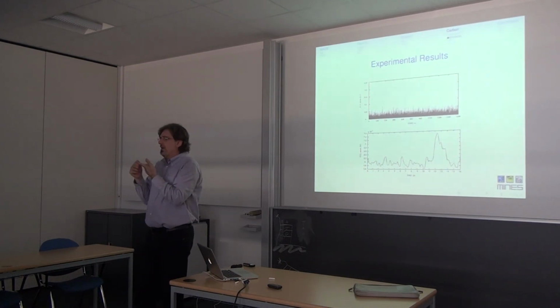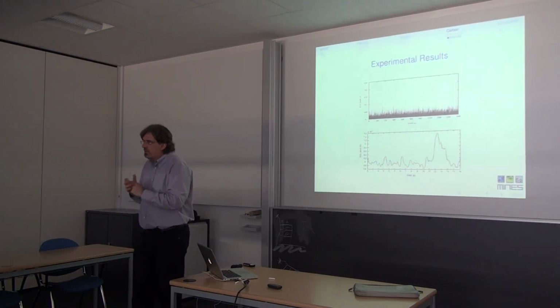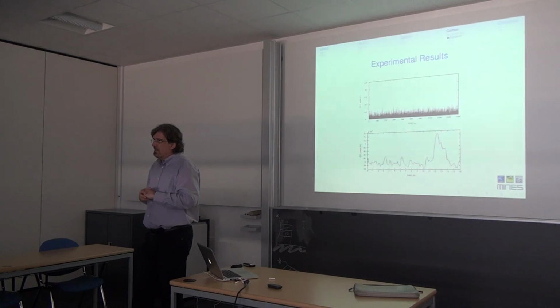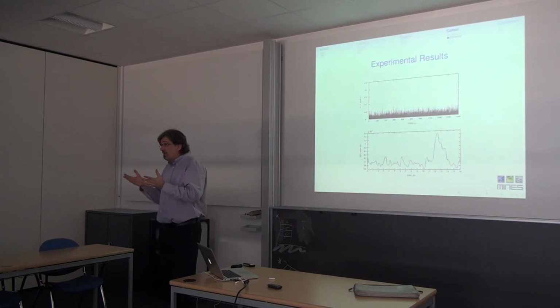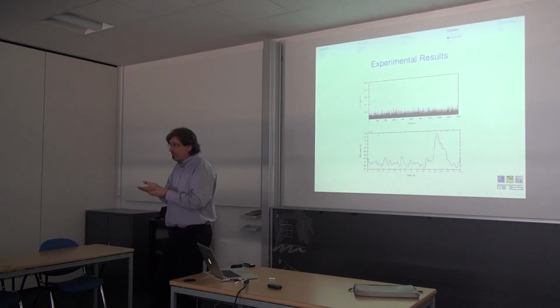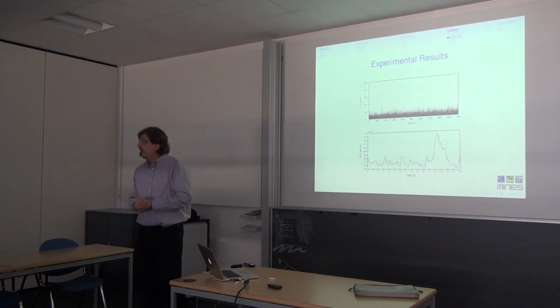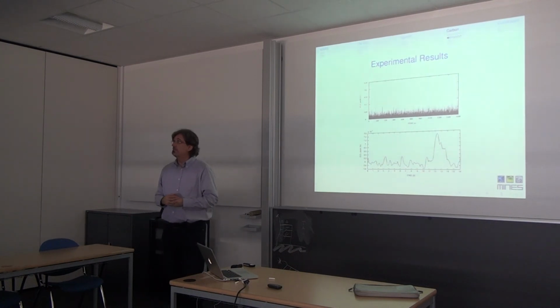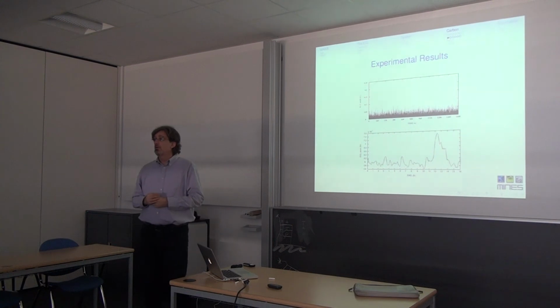Second, you must decrease the dimension. If you lower down the dimension, for sure you will reach better results. And the proof of what I'm telling you is that with glassy carbon it is absolutely reproducible. With glassy carbon, I have a lower signal, but it is reproducible, 100%. Okay?